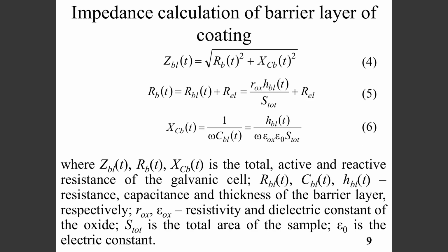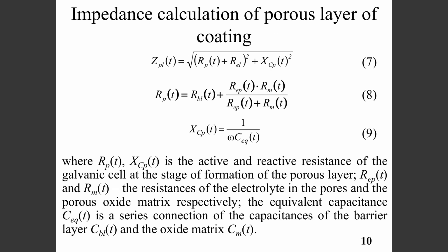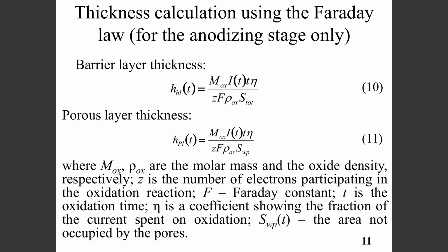A generalized mathematical model of a micro-arc oxidation coating formation, which allows to obtain a fairly complete analytical description of physical phenomena in the micro-arc oxidation process, was also developed. Consider the main provisions of this model. Firstly, on the basis of the previously given equivalent electrical circuit, the expressions from 4 to 9 for the impedance of the barrier and the porous coating layer, by which it is possible to calculate the coating thickness Hbl of t and Hpl of t at the corresponding stage of the anode stage, are obtained. These values can be also calculated using the Faraday's law according to expressions 10 and 11.